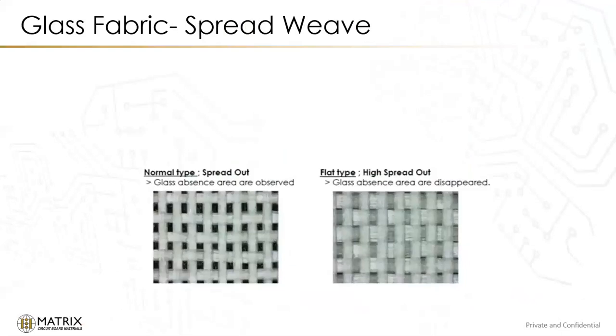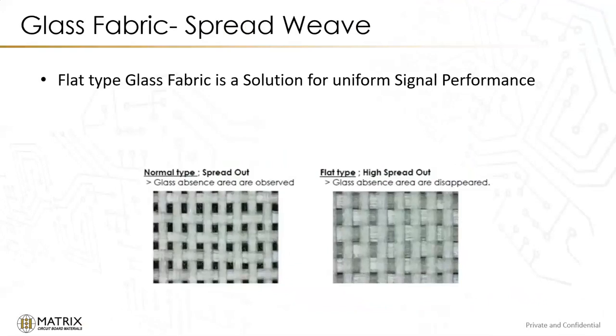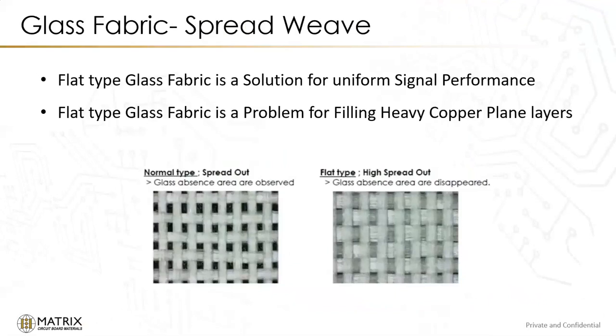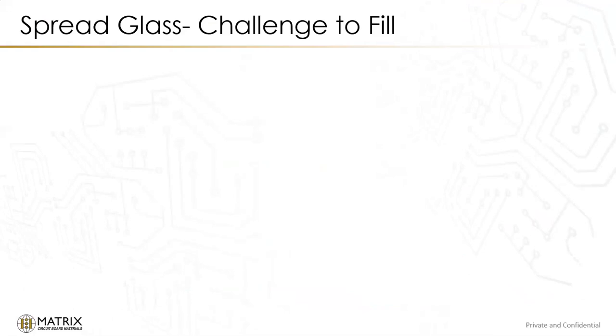But one of the things I don't think gets talked about enough, and it may be just a fact of some of the resin systems that we're using that are lower flowing. So the flat glass is a solution for uniform signal performance, but I would say the flat glass also can be a problem. Actually, it shouldn't be a problem. But really, it's more of a challenge for filling heavy copper. And from the tech service side of things, that's something that has been one of the issues that needs to be educated, especially for new users, and to try to quantify some of that too.